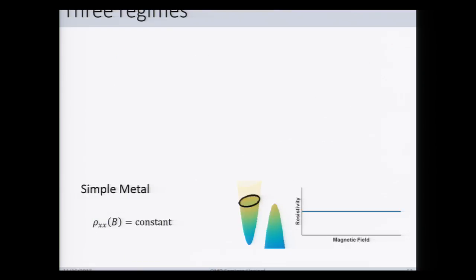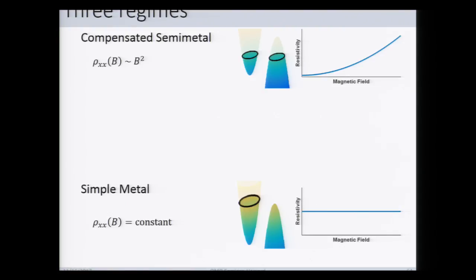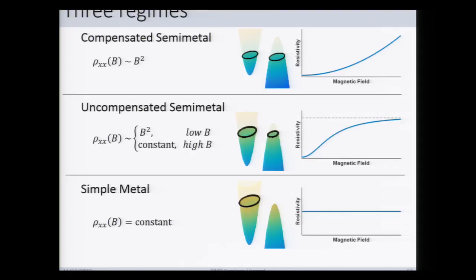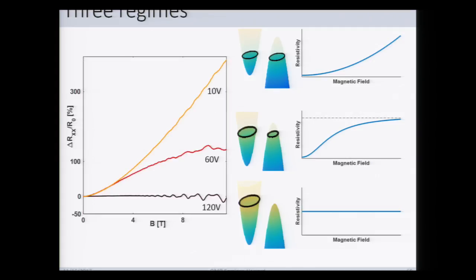So as a recap, for the simple metal, you have a constant magnetoresistance. Imagining here you have, say, a single Fermi surface of electrons and no change in resistivity as a function of magnetic field. For a compensated semi-metal, you have a quadratic increase of the resistance that, according to the semi-classical equations of motion, does not actually saturate ever. So something else will have to kick in at higher magnetic fields to eventually get it to stop. And then finally, you have an uncompensated semi-metal, where if you have, say, both electrons and holes present, but more of one than the other, then you have at low fields a quadratic magnetoresistance saturating to a constant at high field. And this is indeed quite reminiscent of what we have in our devices.